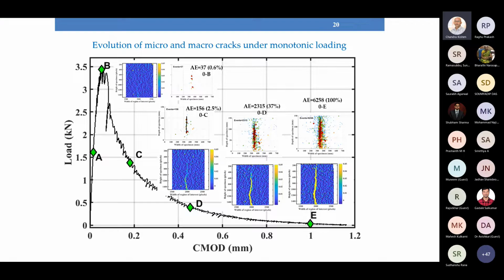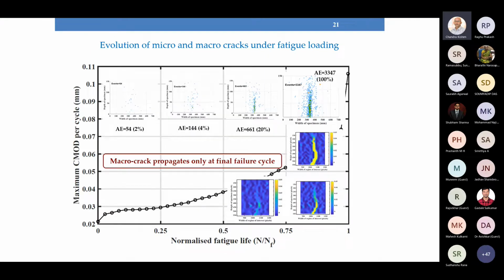Next, under fatigue, we see a different kind of mechanism. Here we are plotting the maximum CMOD on the vertical axis and the normalized fatigue life. The fatigue life is normalized with the final failure value. So 0 to 0.25 indicates 25% of the fatigue life. In the first 25% of the fatigue life, we see only 2% of micro cracks or events have formed, 2% of the final 3,347.